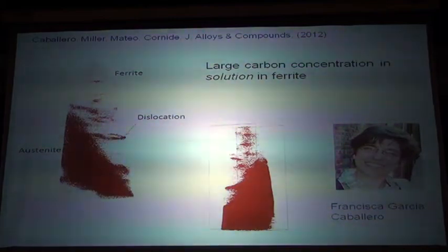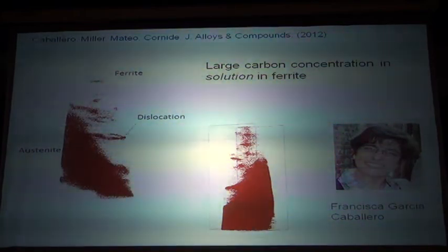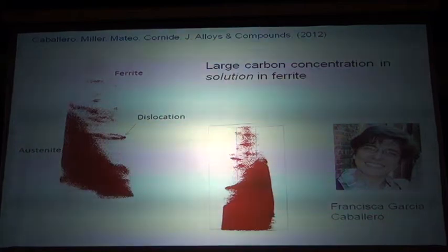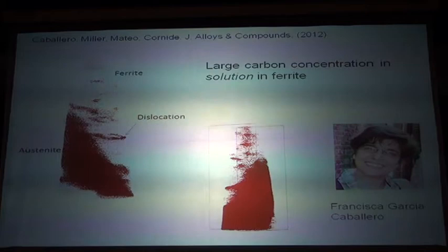The breakthrough in understanding came from the work of Francisca Caballero, who, using one of the most advanced atom probe techniques at Oak Ridge National Laboratory, showed that yes, there is carbon at dislocations, but there is a huge amount of excess carbon in solid solution, because you can look at the region between the defects and show that the carbon is supersaturated in the solid solution if we accept the traditional iron-carbon phase diagram. So this paper, which showed that there is excess carbon in solid solution, caused me a lot of pain. How do we explain this? And after a great deal of...